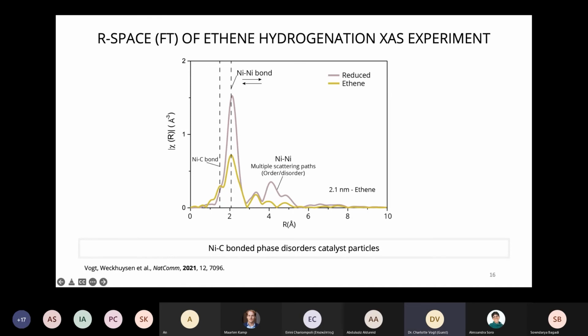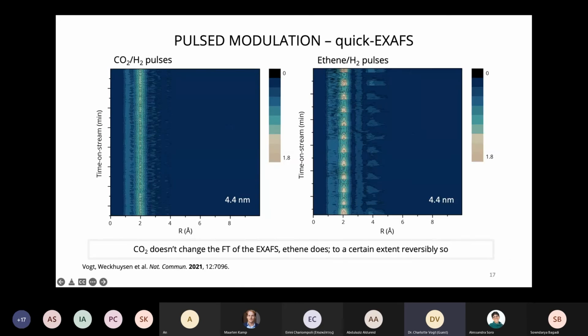And funnily enough, we see local ordering and disordering going from reduced to reaction. And with that ordering and disordering, we see this peak coming up, this nickel-carbon bond. It could only be nickel-carbon in this case because there's no oxygen in this reaction environment. So there's carbon attaching to the nanoparticle, and it's creating a disorder in the nanoparticle.